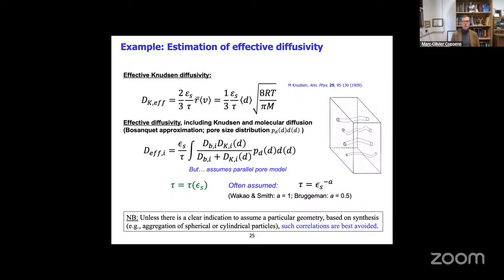So a way then to use this model in practice to calculate an effective diffusivity in a material, if we go back to the simplest models of parallel pore models, tortuous or not, is to calculate an effective Knudsen diffusivity, if it's for pure Knudsen diffusion of gases, using Knudsen's original formula, but then corrected with a porosity and a tortuosity factor. And so here, the average velocity would be the square root of 8 times the gas constant, times the absolute temperature, divided by pi and the molecular mass of the gas. So the heavier it is, the slower the diffusion, as you would expect. If the pore is wider, the diffusivity will be higher.